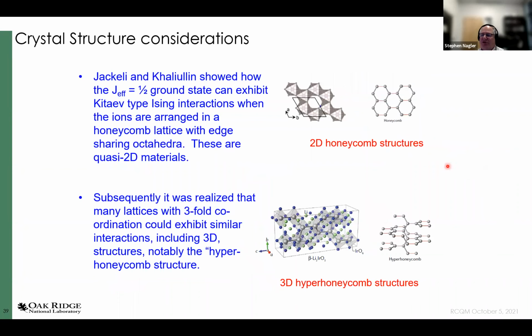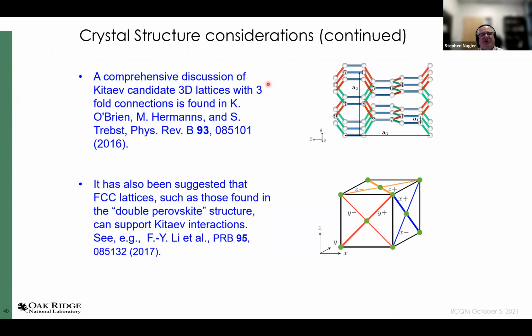Okay, now some considerations about the crystal structure. It doesn't have to be precisely a honeycomb lattice. If you have threefold connectivity, you can get the same thing even in some other kinds of structures, notably the hyper honeycomb structure. So it's really threefold connectivity with these edge sharing octahedra that's important. And by the way, there was a nice article published a few years ago that looked at more or less all of the different lattices that might satisfy that. And it's predicted also that some other kinds of structures, like the double perovskite structure, could satisfy the geometric requirements for this as well.